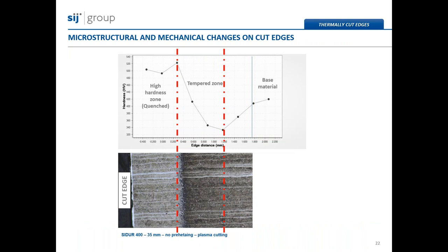Through the webinar, microstructural and mechanical changes in the region close to the cutting line were mentioned several times. They appear only when a thermal cutting process is used, not during cold cutting. On this slide, we have an example on SIDUR 400 grade, which was cut with a plasma cutter. As seen, we have a quench zone with hardness of more than 500 Vickers, and this region with high hardness is approximately 0.2 millimeter wide.